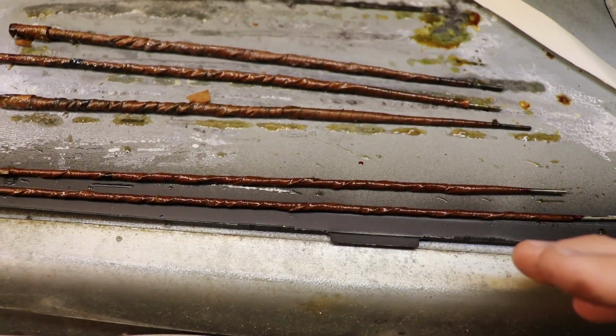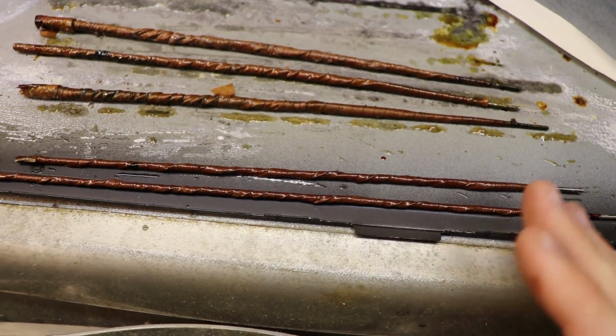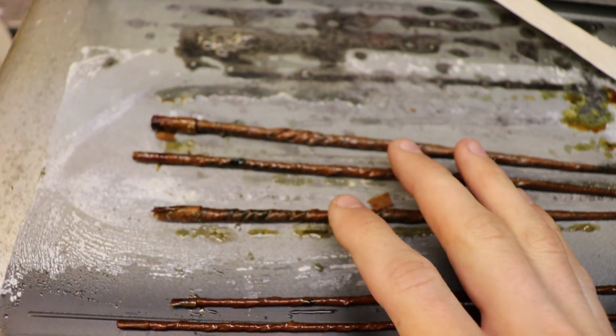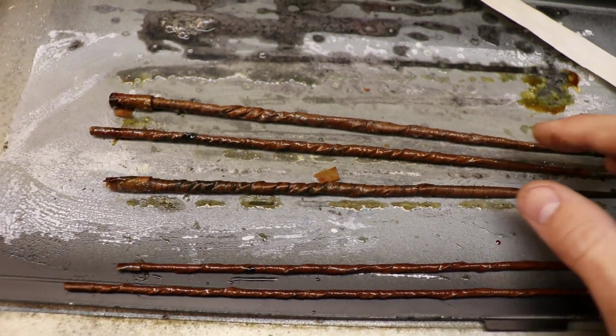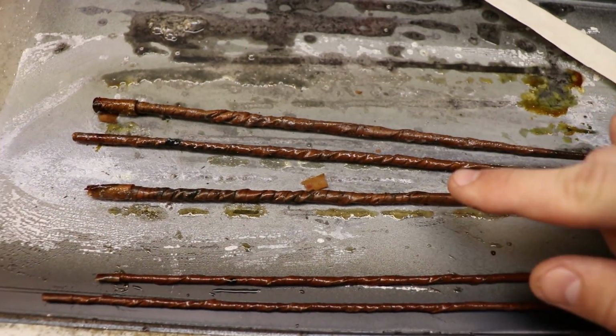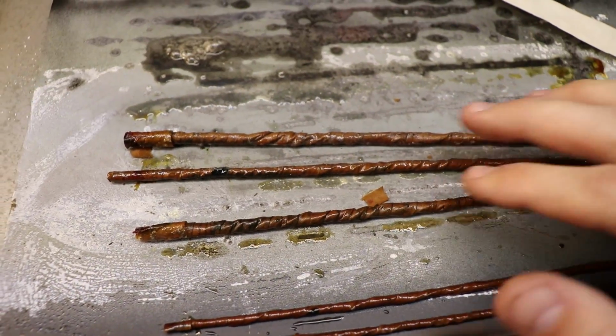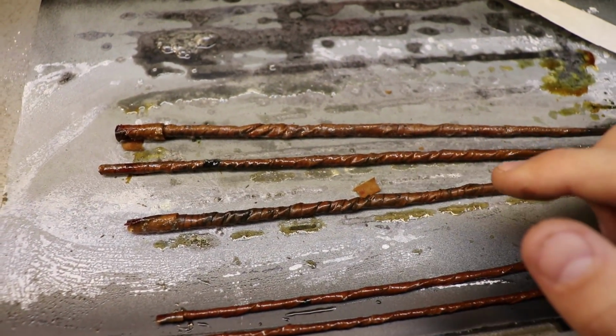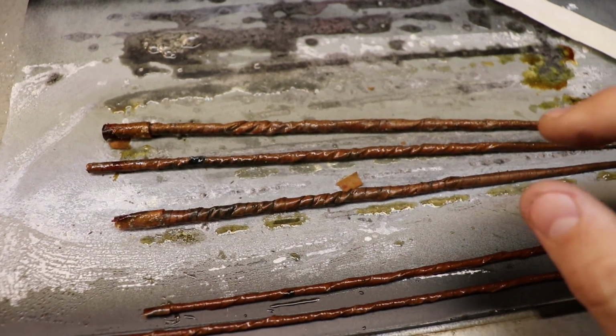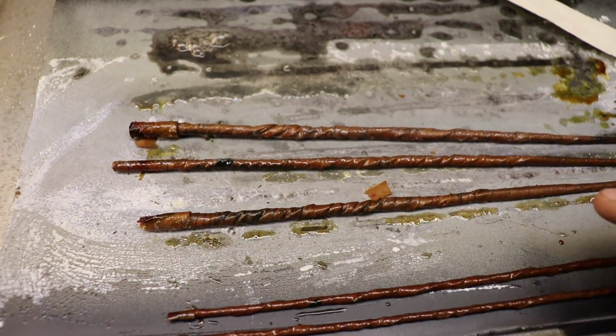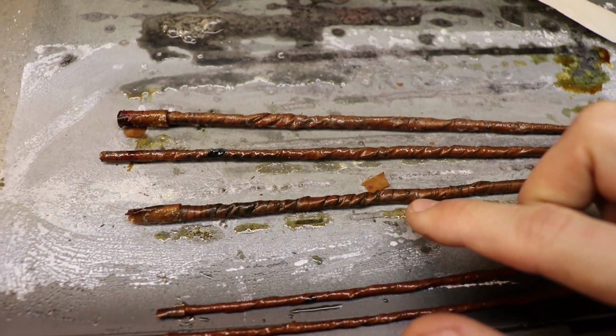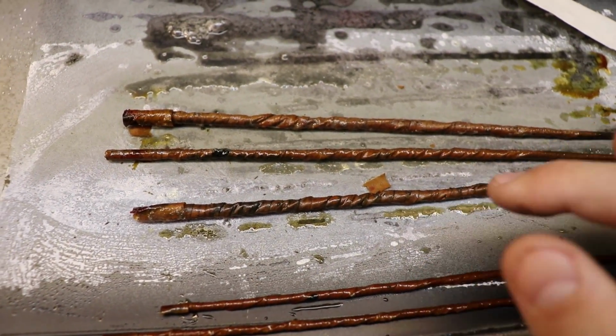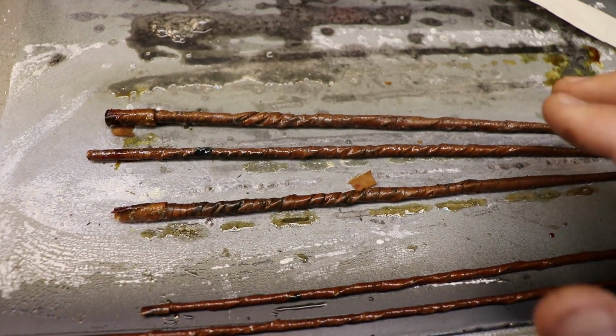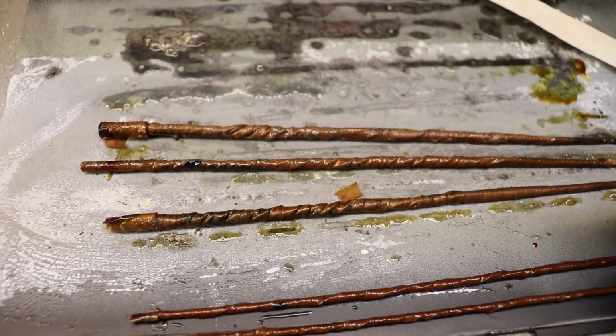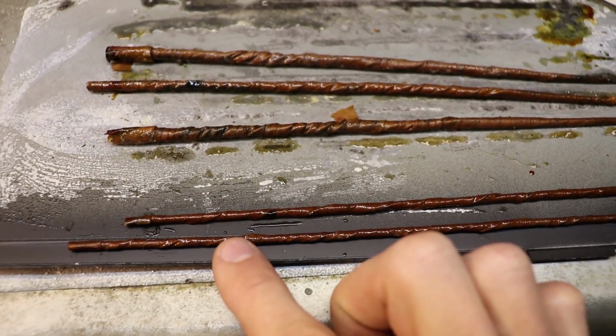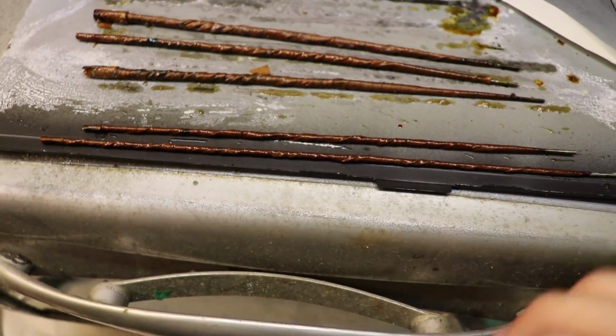to cover them, and I think this is going to result in better performance in the rod. But we'll see, of course. I just noticed that when I looked at these thicker rods with less uniformity throughout the entire rod, I noticed cracks, actually. And I noticed in these rods, because of the thicker wrapping, the wrapping was simply not tight enough around the wire, around the metal, and it was causing air gaps in between the metal and the wrapping. And so that's what you don't want. You want as much uniformity throughout the entire wrapping, and so I think that's why these are going to give the best performance, but we'll see in a second.